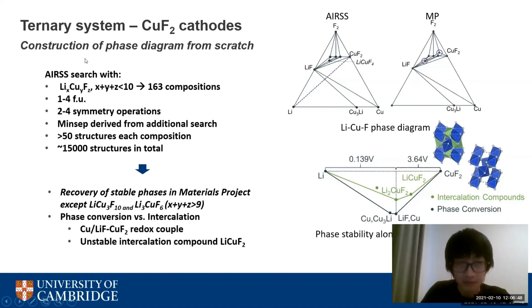For this kind of search, we really need to construct the phase diagram, because in most of the systems we know the chemistry, but if we really do something new, we don't really know the chemistries. We not only need to know the energy of this single phase, we also need to know the other phases in this composition range, so that we know whether this material will decompose into other phases. So we need the energy of all these phases within the phase diagram.